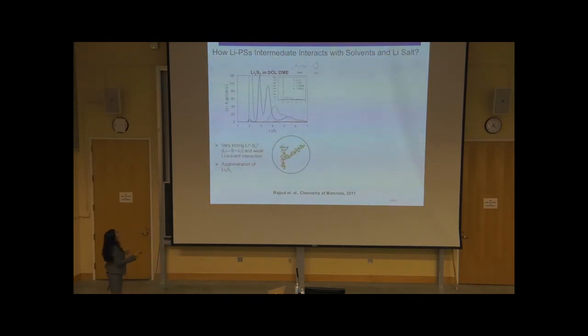And the first question we asked ourselves is how these different lithium polysulfide intermediates react with the solvent molecule and lithium salt in the solution. And we looked at the solvation structure of Li2S2 in DOL-DME solvent mixture. This is one of the most commonly used solvent mixtures in lithium sulfur batteries. And we found that there is strong interaction between lithium and polysulfide species and a very weak interaction between lithium and solvent.